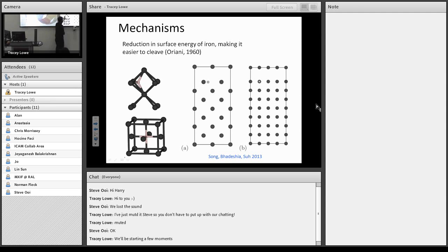Hydrogen in ferrite, unlike carbon, occupies tetrahedral interstices. It sits most comfortably in tetrahedral rather than octahedral interstices. This is tetrahedral; octahedral would be in the middle of that object. Whereas in austenite, it sits preferentially in the octahedral interstices.